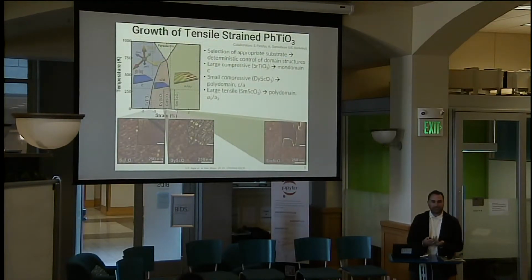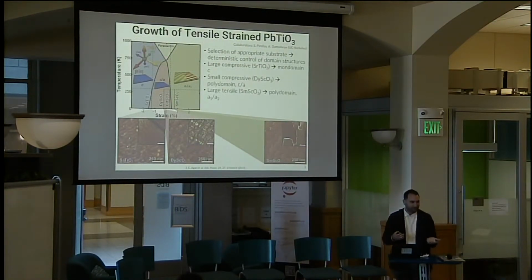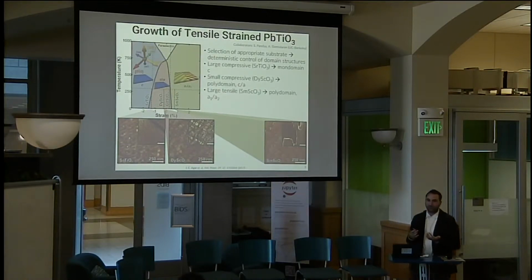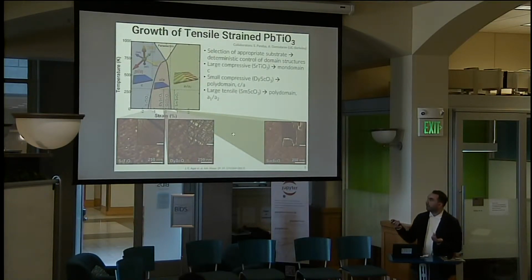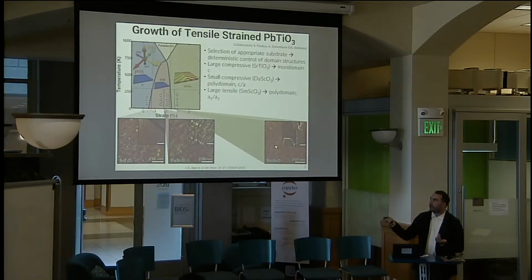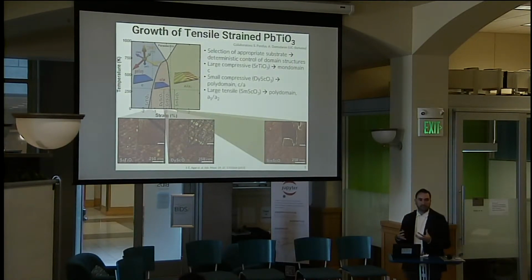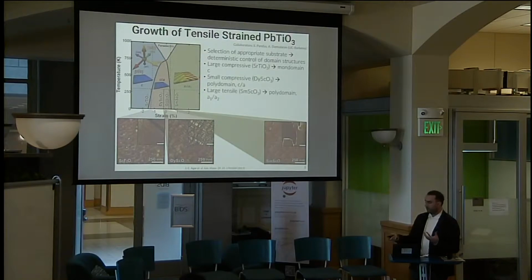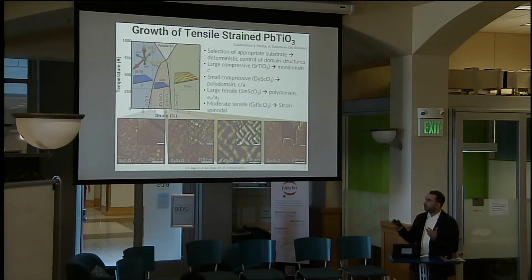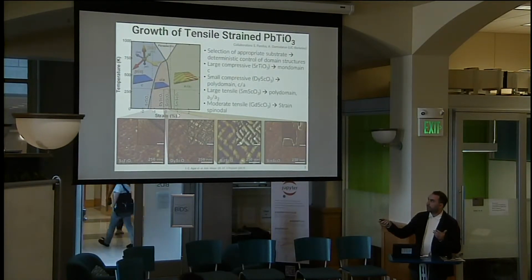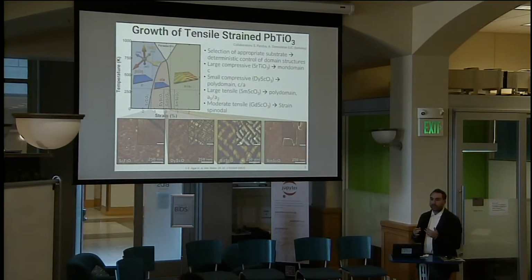I actually make materials. I'm an experimentalist. I do a technique called pulsed laser deposition, where we grow materials at the atomic scale, and this is just an example. One area we focus on is designing these materials using strain, pulling on the lattice in different directions to alter how the material breaks down into different structures. As a design rule, we try to focus on regions where you create competition between different phases, which allows you to transition between them by applying a perturbation, such as an electric field or mechanical force.